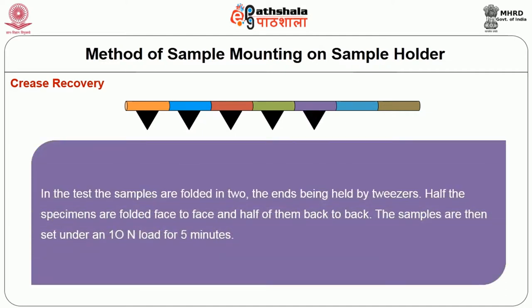The test samples are folded in two. The ends are held by tweezers. Half the specimens are folded face to face and half of them back to back. The samples are then set under a load of 10 Newton for 5 minutes.